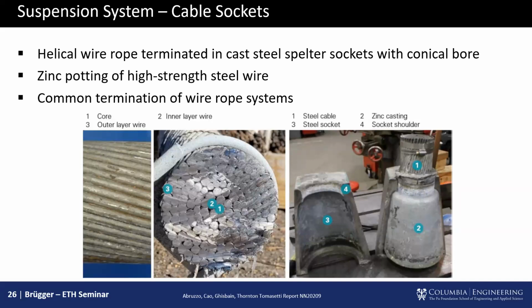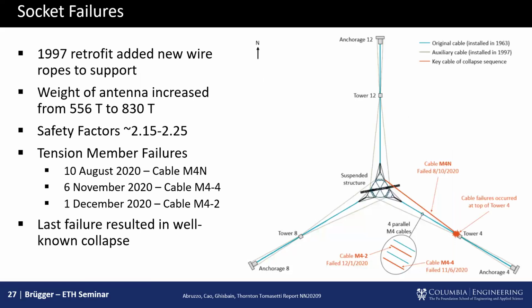And this is also very common for elevator ropes and, of course, for suspension bridges, say, built after World War II. Now, this telescope, and this is essentially to scale, you can see, is hung from 3 very large towers. And during the upgrade in the 90s, that's when the telescope's weight was increased significantly. And these extra sets of wires were added, and they were actually added eccentrically to the main anchors, mostly to provide torsional rigidity of the telescope. But of course, by doing so, they did change the structure and the load significantly. It only had a design safety factor of 2.15 or 2.25, so that's quite low. So they went into this being quite lean already.